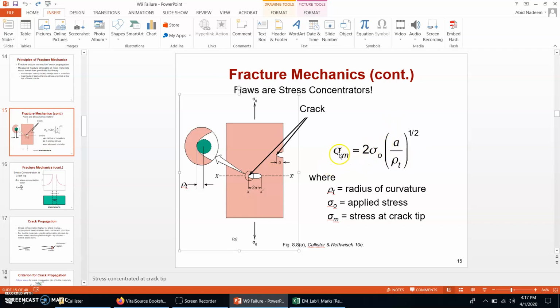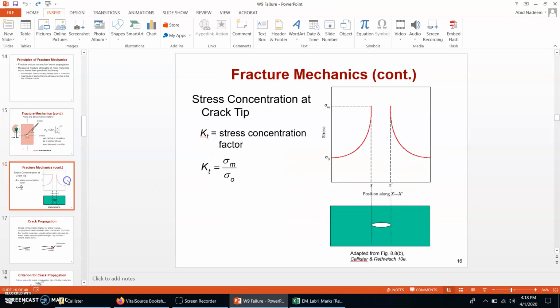So we get this equation, which is sigma m equal to 2 sigma naught times the square root of a over rho t. Sigma m is the stress at the tip of the crack, sigma naught is the normal applied stress, and a, as I already explained, is the length of the external crack, and rho t is the radius of the crack tip. We can use this equation for our numerical problems. Next, we can discuss this slide.